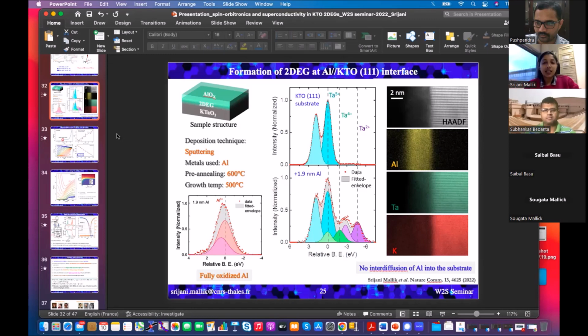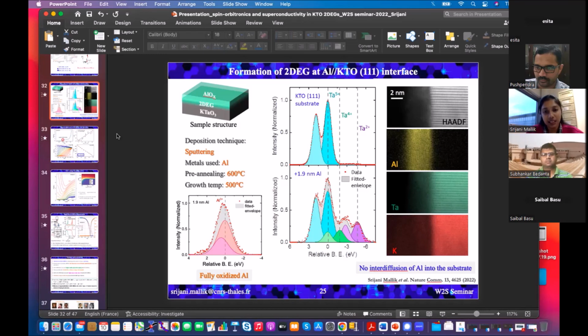Actually, KTO 001 is cubic, but if we consider KTO 111, then it becomes hexagonal. So there is inherent anisotropy in KTO 111. And in principle, for KTO 001, nobody could achieve superconductivity so far. So as you said, for sure there is a huge contribution of anisotropy in the origin of superconductivity. But we really do not know the exact reason of the superconductivity, but it's very much anisotropic in nature. And when we measure at different crystal directions, we also get different TCs.